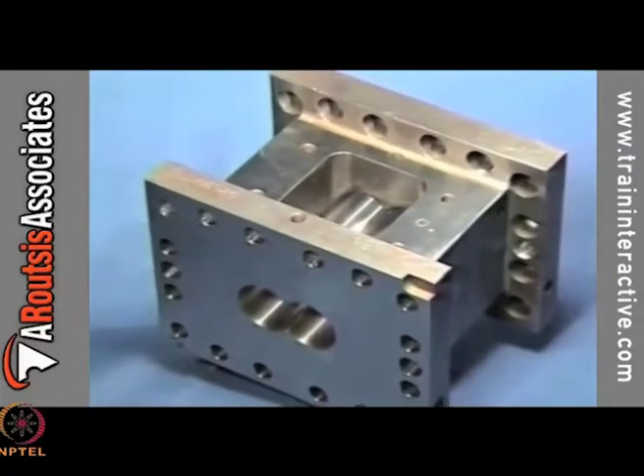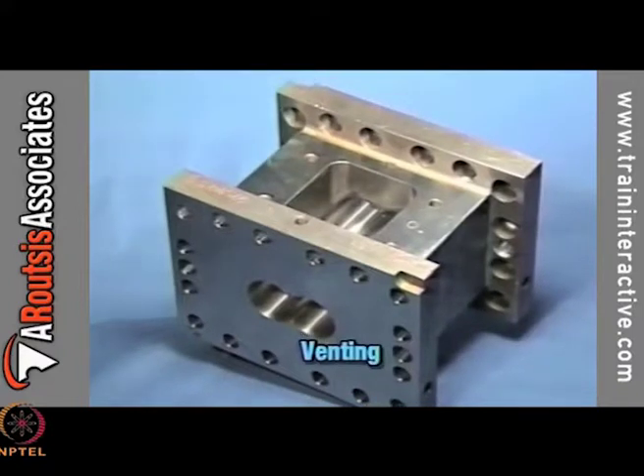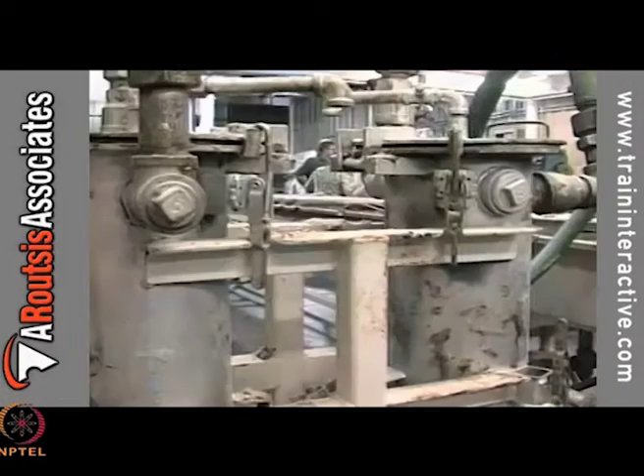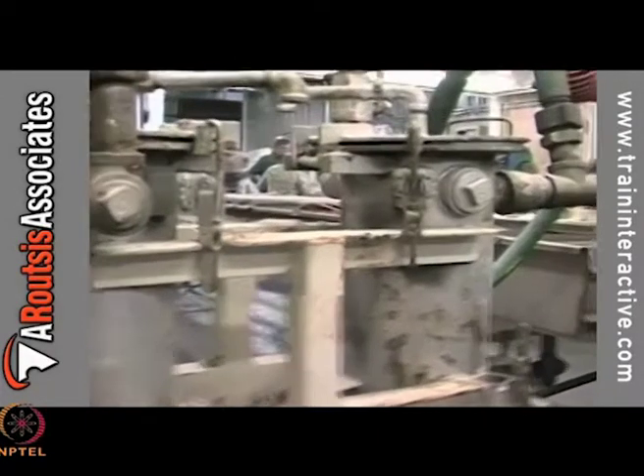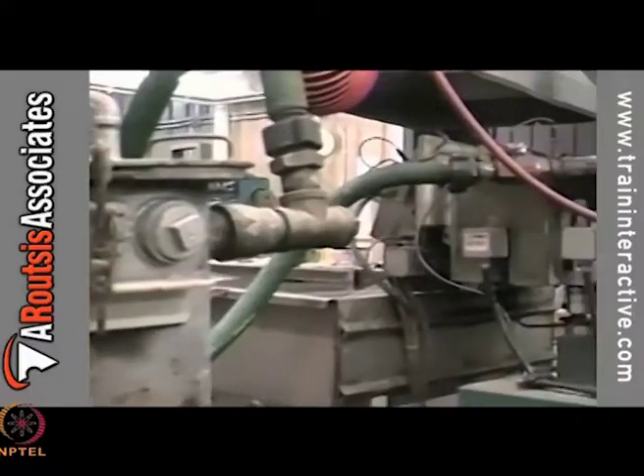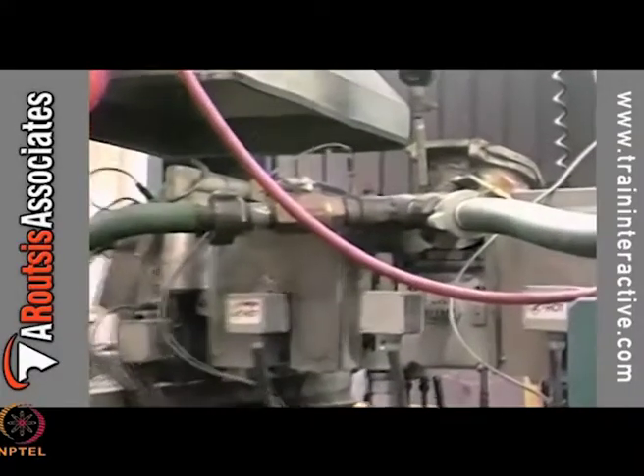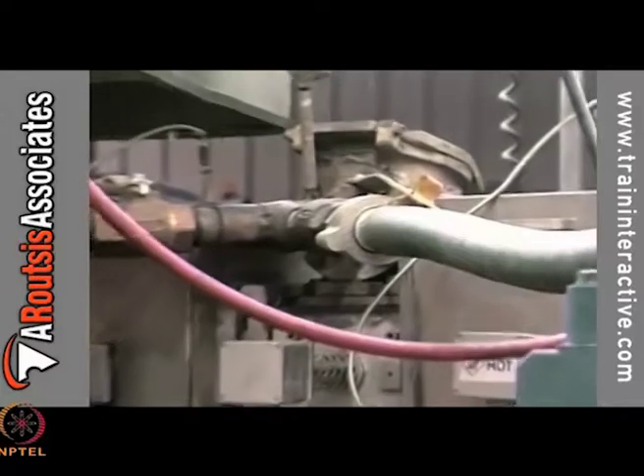In either type of machine, trapped air from the feed and gases or vapors from additives must be removed from the plastic before it enters the die. Venting is done by releasing the pressure on the melt, usually with vacuum applied, while constantly mixing the material. Any bubbles in the material will expand and break as they come to the surface, releasing the gaseous material. Co-rotating compounding extruders often have several vents.